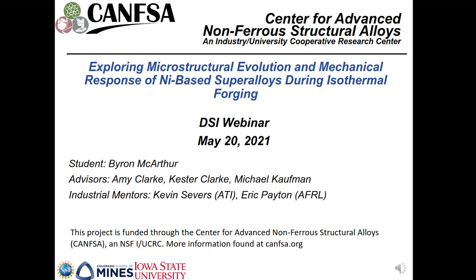I will note that while most of my work early on was done at about 10^-3 per second, there were definitely strain rates that I was able to achieve abnormal grain growth with, about 10^-2 per second. I think anything faster than that, we really weren't seeing abnormal grain growth. To reiterate my point earlier, I think locally within microstructures, this abnormal grain growth is inconsistently occurring sometimes based on differences in processing conditions. But this does seem to be consistent from what I've seen and heard from industry. If you have other input or information on that, I'd definitely be interested in hearing about it.